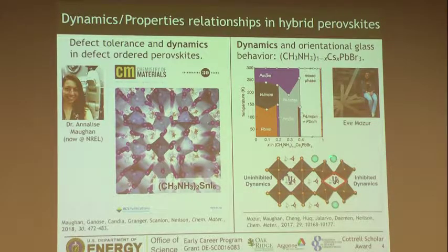Well, it turns out when you put in small amounts of cesium, you effectively freeze them. You inhibit their dynamics, and they behave glassy. So you observe thermodynamics that resembles that of a glass, even though you have this crystalline framework that you can use crystallography to study. So these fascinating materials, and the properties all follow these rich phase diagrams.